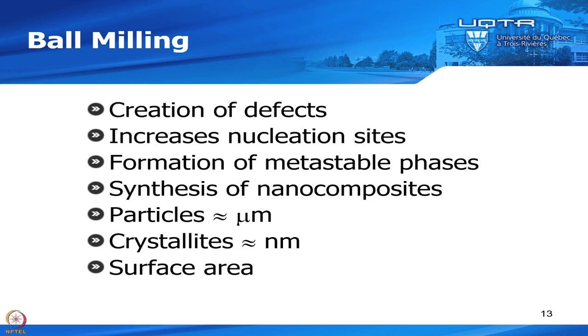Of course, you could synthesize nanocomposites, so you could mix two alloys and you could get a nanocomposite. Usually when you do ball milling, the particles are of the order of a micron, but the crystallites are of the order of nanometers. So you have to be careful when we talk about nanocrystalline material. It doesn't necessarily mean that the particles are nanosized. It's the crystallites that are nanosized, okay? Sometimes in the literature, you see people talking about grain size, but I don't like to use this word because for some people, grain may mean particle, and for some other people, grain may mean crystallite. So I prefer to talk about particle and crystallite, and then it's clear for everybody.